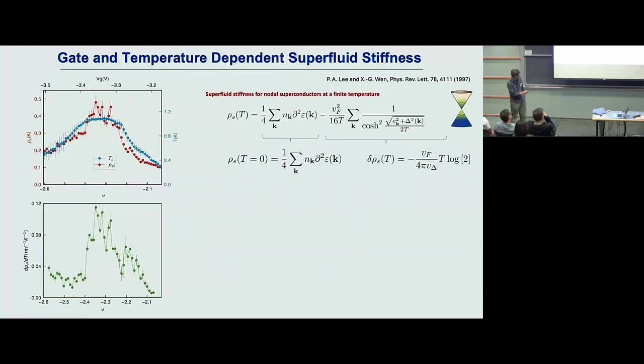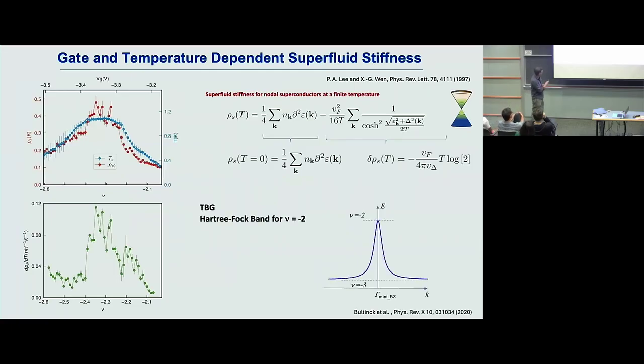So since we have these equations, in some sense, we can first qualitatively explain whether we can explain this behavior. The first thing we can see is that if I assume any band, let's say the Hartree-Fock band for the broken symmetry state nu equals minus 2, that is a model state I can start with. We all learned from this paper that the Hartree band structure is something like this. It's heavier on the electron side and lighter on the hole side, right?